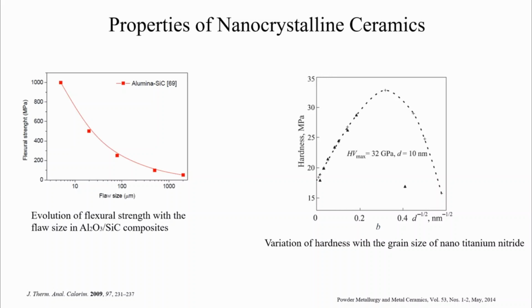The mechanical behavior of nanocrystalline materials has been extensively studied in over 500 publications and several review articles. Many of these studies have found that the yield stress and the microhardness of nanocrystalline materials can be significantly higher, typically 2 to 10 times higher than those for coarse grain polycrystalline materials with the same chemical composition. These findings are often explained using empirical relationships such as the Hall-Petch relationship, which describes these enhanced mechanical properties in nanocrystalline materials.